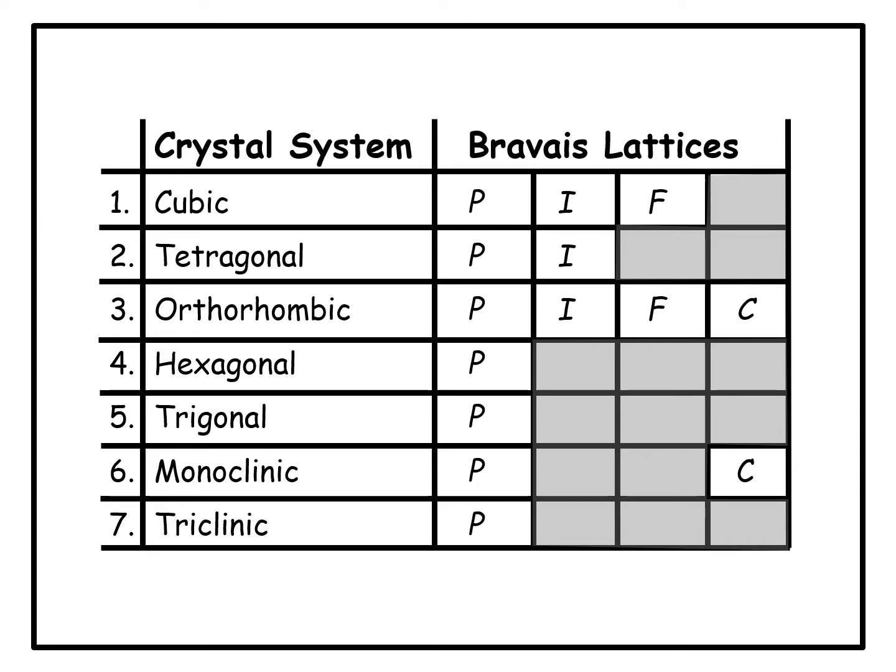And then these crystal systems are further subclassified into Bravais lattices, which are shown here by symbol P, I, F, and C. P stands for simple, I stands for body-centered, F stands for face-centered, and C for end-centered. Actually, C can be replaced by A or B depending on the situation, and this was explained in a previous video of this series. So, we see that 4 possibilities are there for the orthorhombic crystal system.